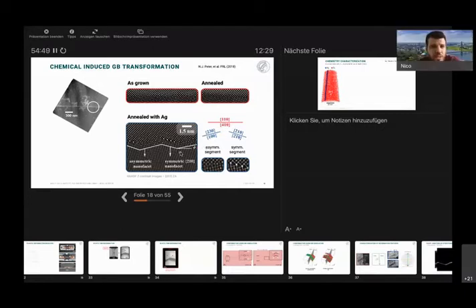Yeah, that's a wonderful question, actually. So I think the angle that I was giving here, this angle right here, is very specific to this specific case in terms of this boundary and this solute element. If we take a different boundary initially, which is further away from the 210 symmetric part here, that might be a very different story, because then it needs to incline much more to get to the symmetric boundary. And the symmetric boundary might be favorable because it itself has already a lower energy than all the asymmetric boundaries that are around it in the energy landscape. So I think it's mostly a function of the boundary type that you have initially.